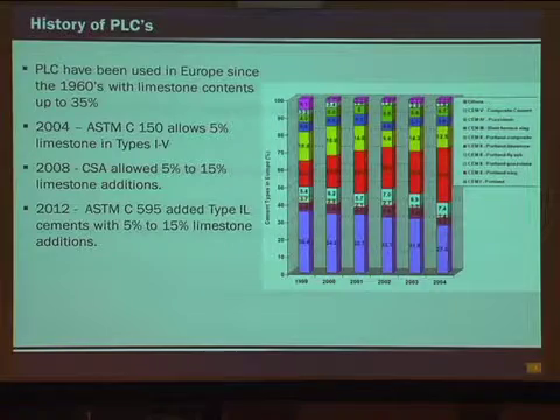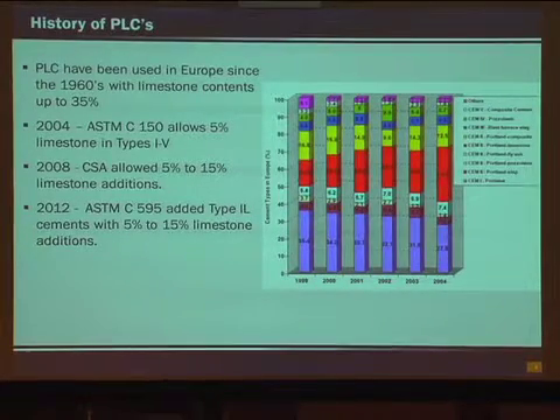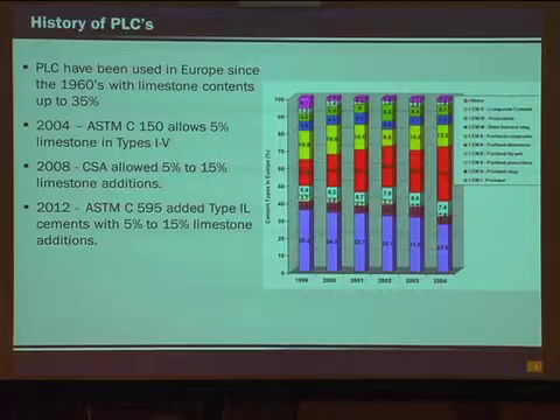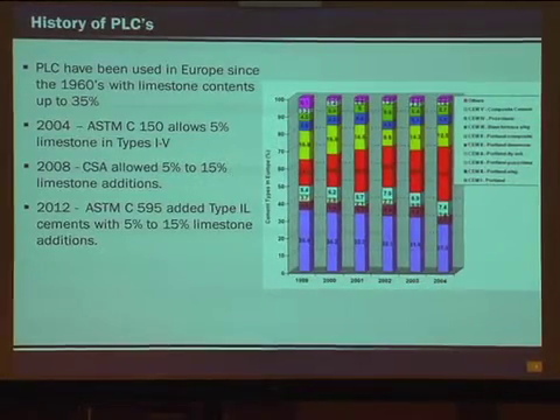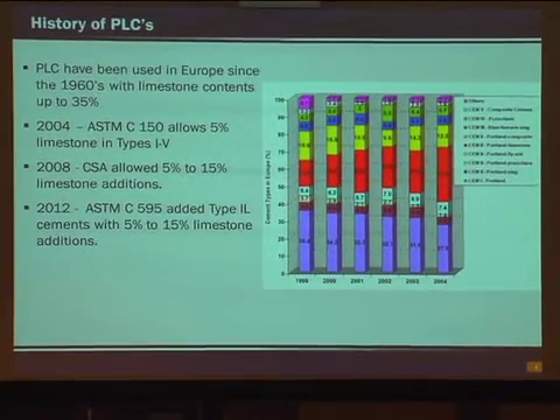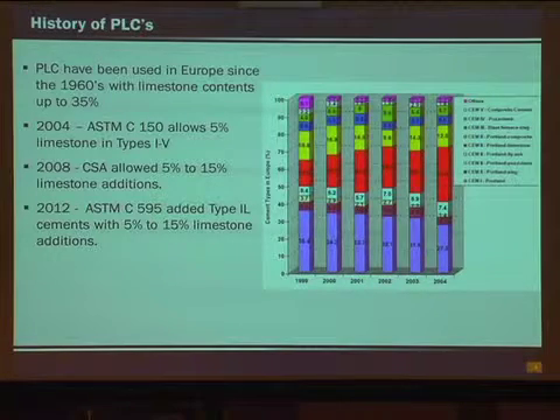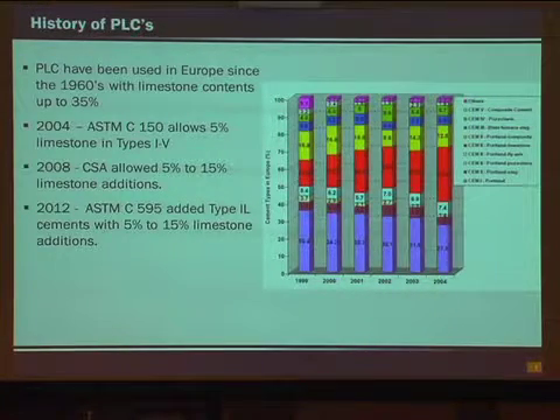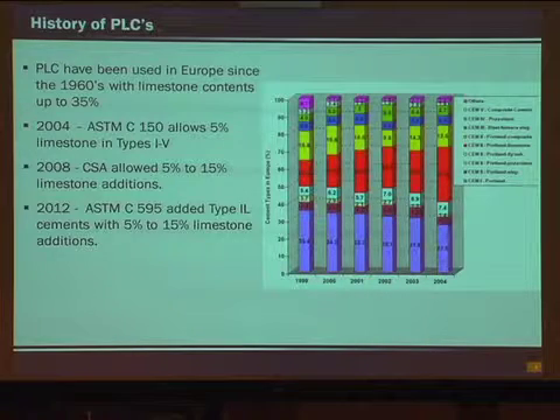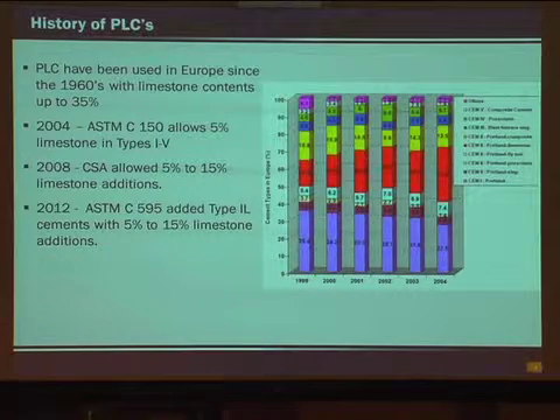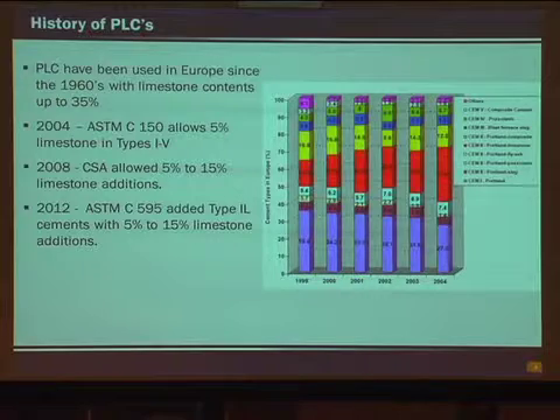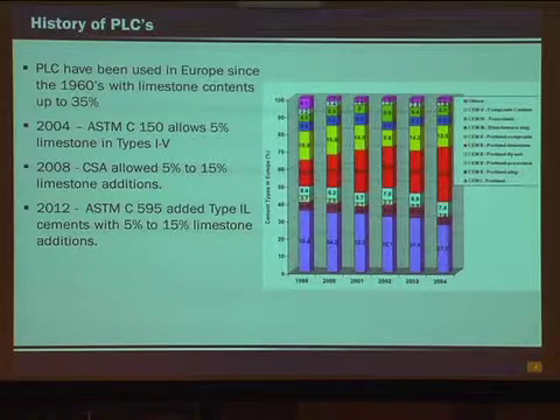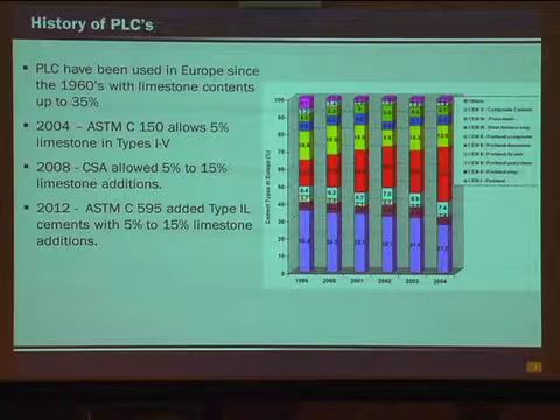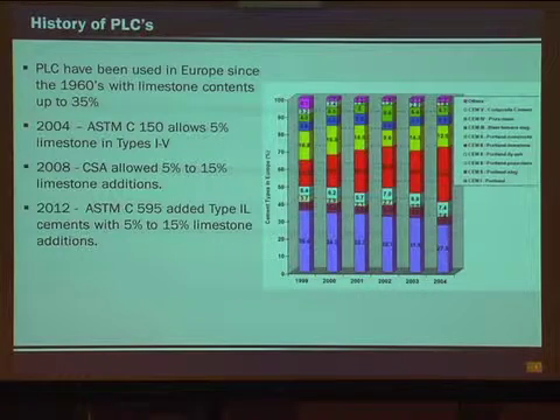In 2004, ASTM C150, which is the primary cement specification, started to allow up to 5% limestone addition. So any cement you get right now in the field probably has about 3.5% limestone. They're restricted to about 3.5, even though we allow up to 5, because of other specification limits. An LOI limit restricts them from going to 5%. We're working on that through committee and trying to raise that so the cement producers can get up to 5%